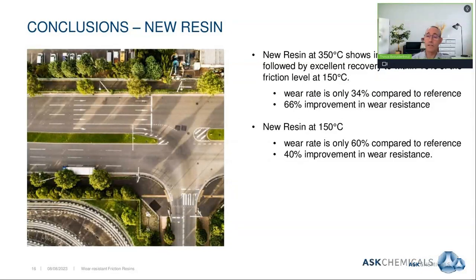If we look at the cold temperature or lower temperature performance, we saw that the wear rate was about 60% compared to the older technology, which, in other words, interprets into a 40% improvement in wear resistance. You may also recall that there was a substantial improvement in the shear strength with this new technology.